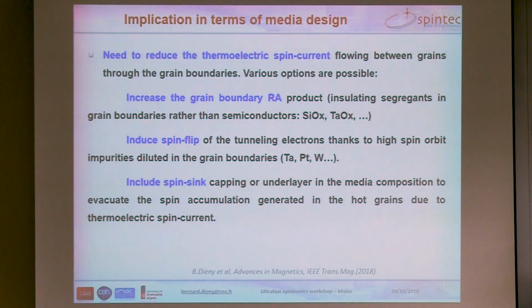So several things can be done concerning the media. One first thing is to increase the grain boundary resistance-area product by using insulating material instead of semiconductor material, like silicon oxide, tantalum oxide, instead of carbon or this kind of elements. Problem is that people actually already switched from oxide to carbon because the growth of the grains and the cylindrical shape of the grains is much better with carbon than it is with this kind of oxide. So that's why people decided to move to carbon. But carbon has this drawback of having a lower resistance-area product and also higher thermal conductivity than this oxide. So in terms also of lateral heat diffusion, carbon is not as good as this kind of oxide.